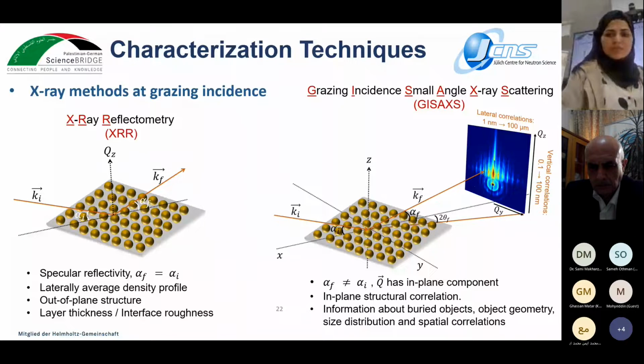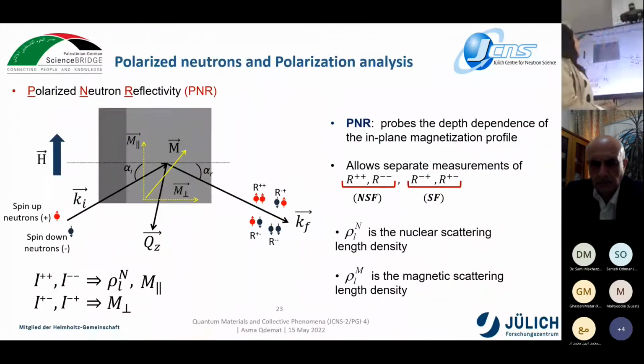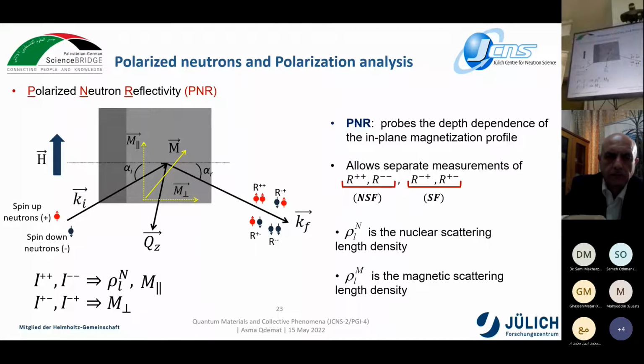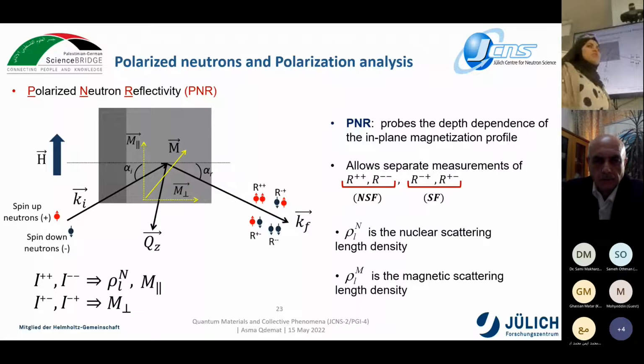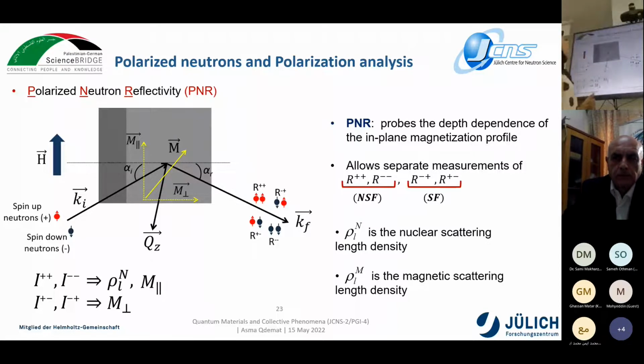The other technique that I use is polarized neutron reflectometry, using polarized neutrons, and this was performed at the MARIA reflectometer, which I'm going to explain later in the next slides. From this technique, we can probe the depth dependence of the in-plane magnetization profile. So we can get insight into the internal magnetic properties of my particle film.